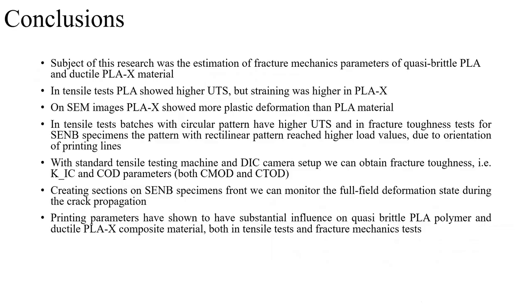So to conclude, the subject of our research was the material behavior of regular PLA material, vastly used in FDM technology, and one particular material with some additions with which one manufacturer hoped to get different mechanical properties and put more advantages in the created material. PLA is good because of its dimensional accuracy, but because of its brittle behavior, it doesn't have many functional applications. We've seen how printing parameters influenced the tensile test results, namely the ultimate tensile strength, and which parameters gave the best results.